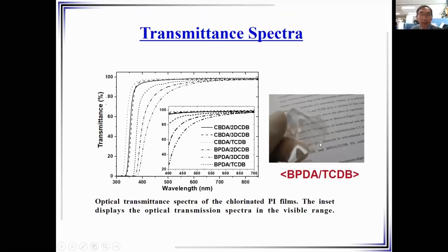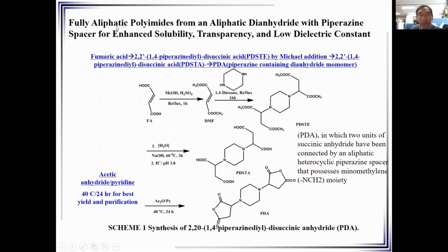So this is one idea. We could develop new colorless and transparent polyimide by using brand new dianhydride or diamine. And in the same series, we developed a new fully aliphatic polyimide from an aliphatic dianhydride with piperazine. And finally, we made a brand new dianhydride here, PDA. Here we introduced this group, piperazine, and we could reduce the charge transfer complex formation. And what was the result?